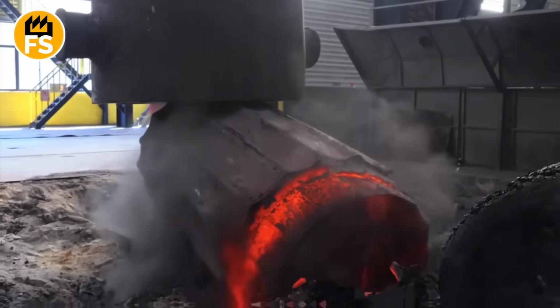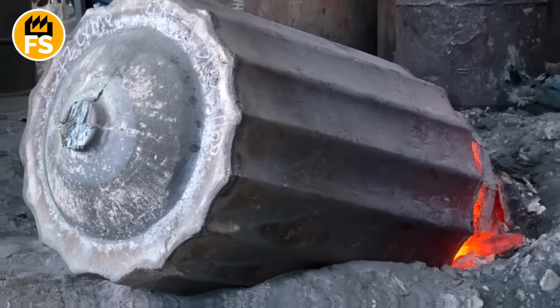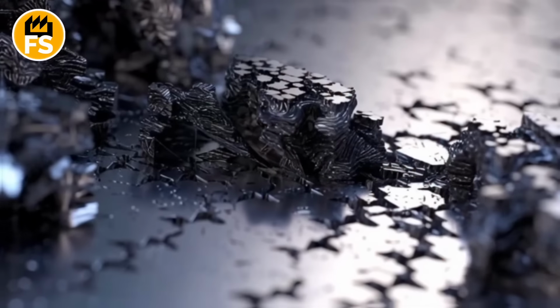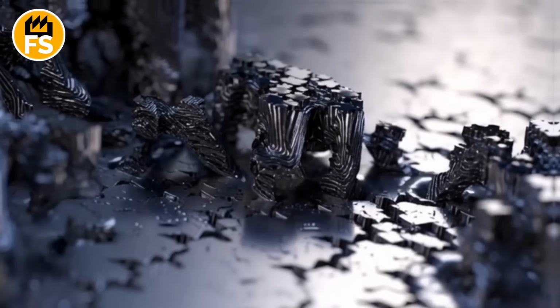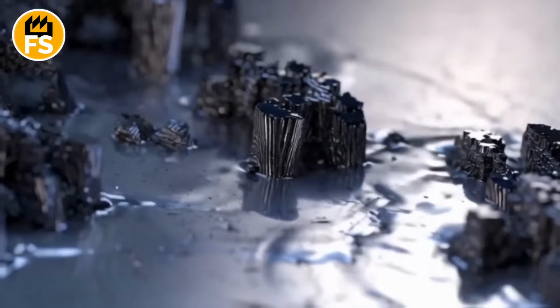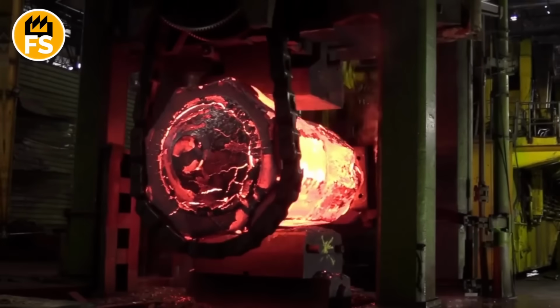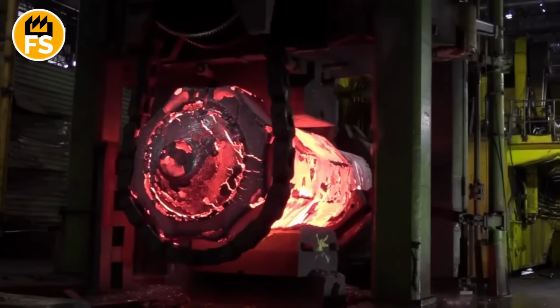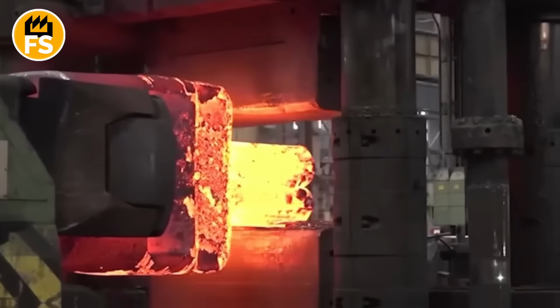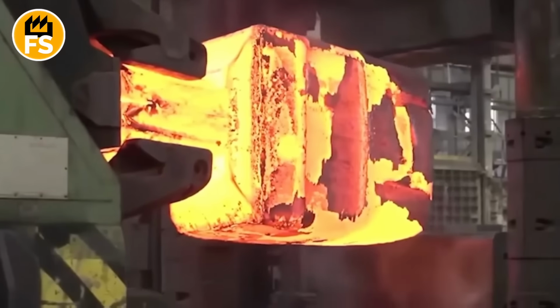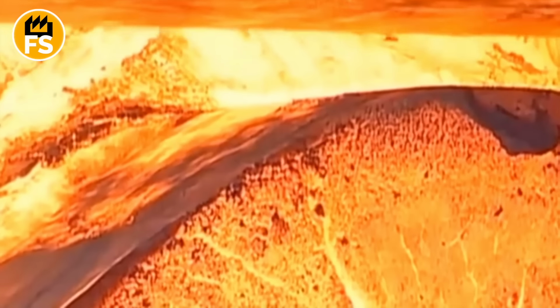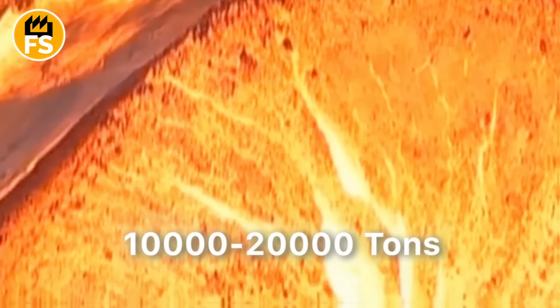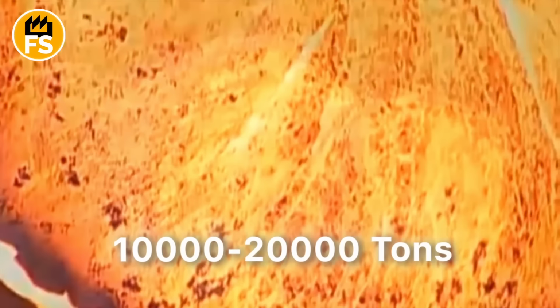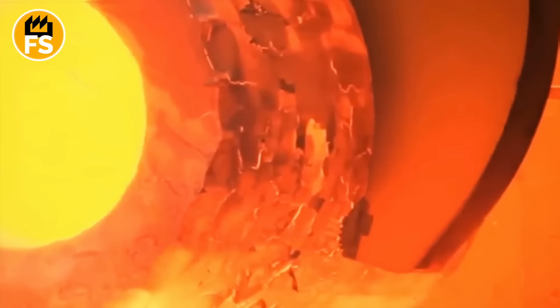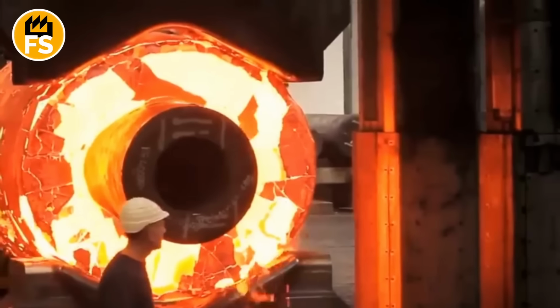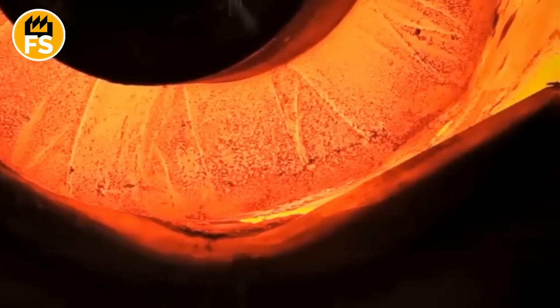The extracted ingot, despite its weight, is not yet a finished blank. It has a cast, coarse structure with large crystals. To transform it into strong, homogeneous metal capable of withstanding extreme loads, forging is required. Forging 500-ton ingots demands hydraulic presses with working forces ranging from 10,000 to 20,000 tons. For example, forging the largest reactor components requires presses with a capacity of 40,000 tons.